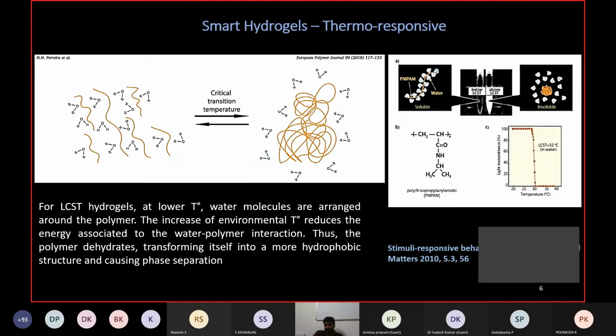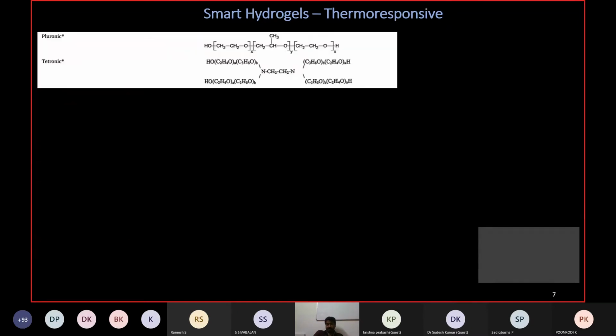And you look at the temperature change and the performance and the transformation of the structure is, see, exactly at 32 degrees centigrade that happens. So the structural change is there at a particular temperature, and that temperature also should be mentioned. So that the temperature is finally the change in the conformation or the change in the structural form that allows the tuning of the hydrophobicity and hydrophilicity. So you are making the structure responding to temperature and changing its structure that helps the release of the drug or loading of the drug.